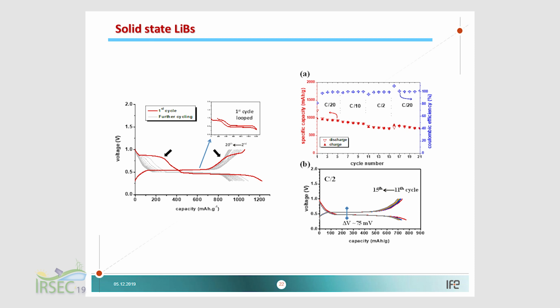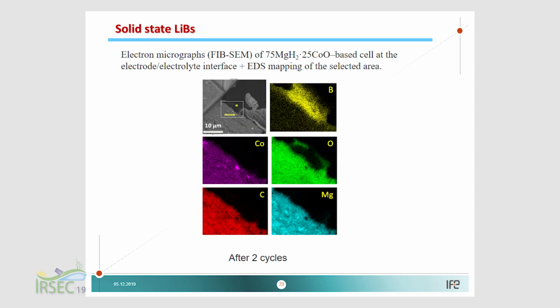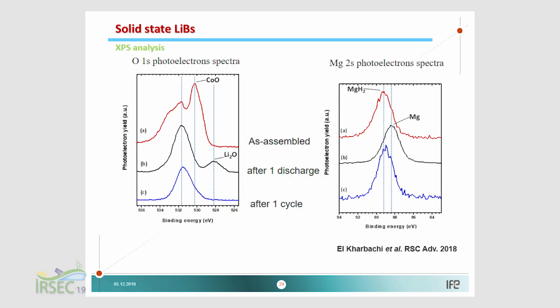We also did some rate capability tests, which look quite interesting, without really a lot of change in the capacity, which is quite stable during 20 cycles. We also looked at the interface, and XPS confirmed the reversibility in a parallel way. I mean, there's no interaction between the cobalt oxide and magnesium hydride.